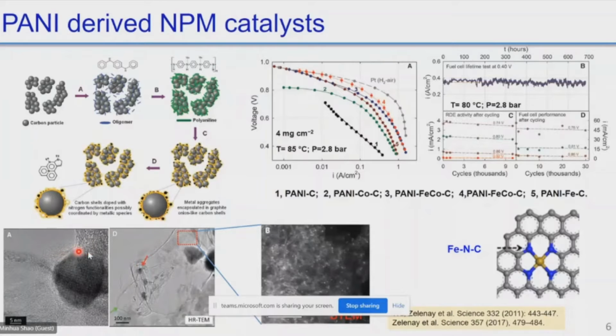And at that time, you could see some nanoparticles, and we could not find out which was the real active site. Later on, with very advanced microscopy, we found that in those empty areas there are actually some single atoms, iron coordinated with nitrogen and carbon. So that will possibly be the real active site.